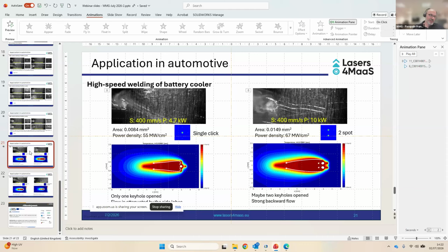Yes, that is our starting point, our baseline. The beam oscillation, or beam wobbling, is okay, but with the galvo scanner you are around the kilohertz scale, and with kilohertz you can't go faster than 200 millimeter per second welding speed. If you want to go much faster, we have to add other dynamics, and the classical wobbling technology is simply not fast enough to cope with the actual high speed of the laser beam itself.